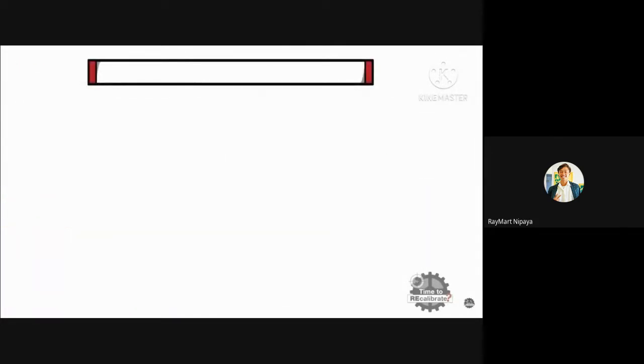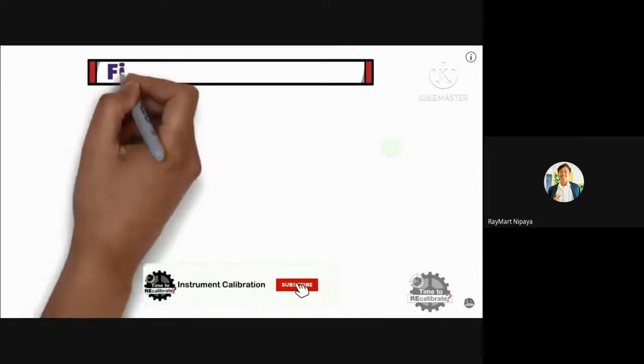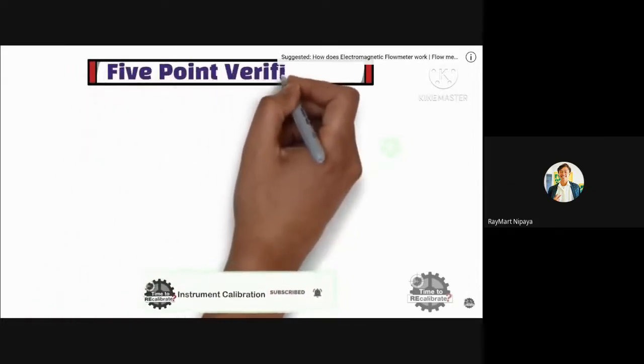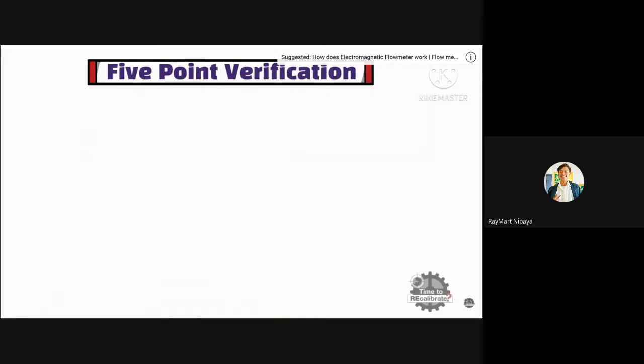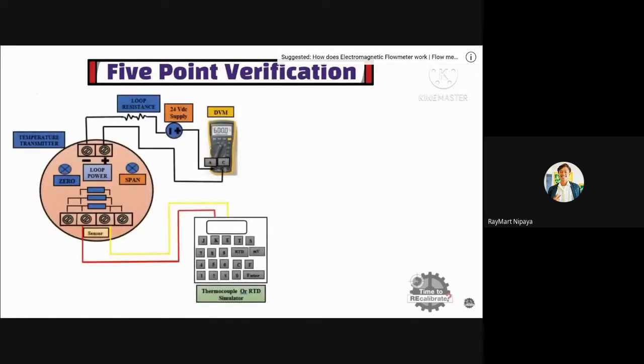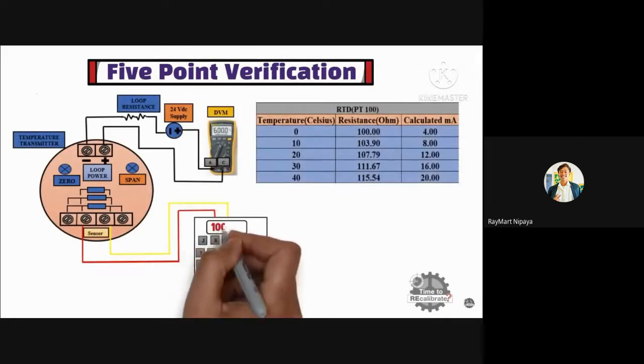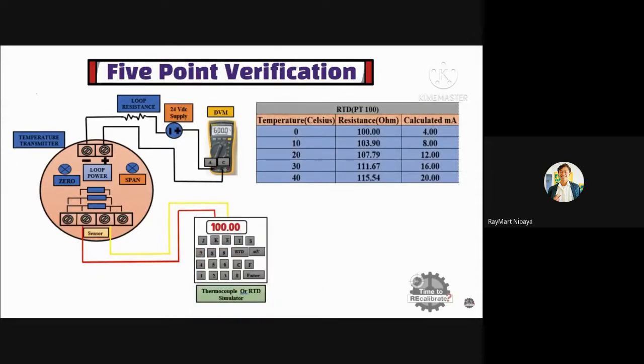Once you are done with zero and span calibration, we need to perform a 5-point verification test to check the calibration. First of all, apply 100 ohm resistance value to the transmitter, and check the value in the DVM. The measured value should be 4 milliamperes. After this, apply 103.90 ohm resistance value to the transmitter, and check the value in the DVM. The measured value should be 8 milliamperes.